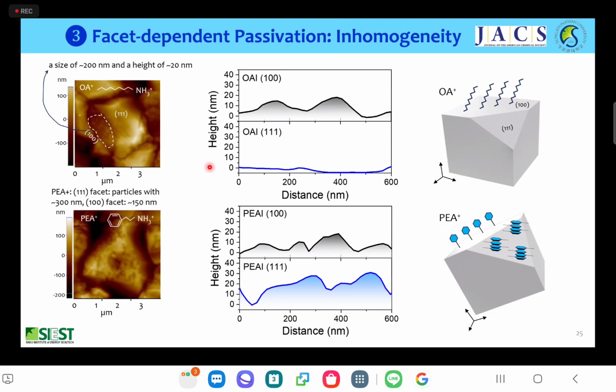After making the perovskite film, people would like to passivate the surface of the perovskite film. People use octyl-ammonium bromide or iodide materials. Interestingly, we found that this kind of material is adsorbed only on the 100 crystal facet, and it acts as a repellent for the 111 crystal facet. We then changed to phenethylammonium iodide, which people also use frequently for passivation. However, we found that there is a different adsorption depending on the crystal facet.